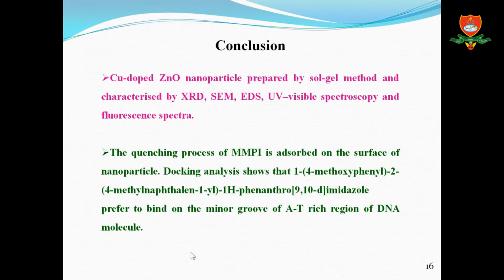Conclusion: copper-doped zinc oxide nanoparticle prepared by the sol-gel method and characterized by XRD, SEM, EDS, UV-visible spectroscopy, and fluorescence spectra. The quenching process of MMPI is adsorbed on the surface of nanoparticles. The MMPI prefers to bind on the minor groove of the A-T rich region of the DNA molecule.